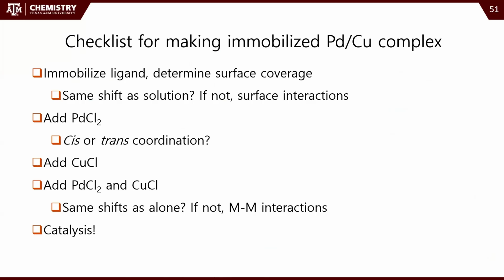This is kind of a tall order, and because it's an immobilized complex and the surface coverage of the ligand is not so good, we only really have solid state NMR as our analytical technique. XPS is too insensitive. X-ray diffraction is insensitive and gives not particularly useful data. Same with FTIR. You can tell they're different materials, but it's difficult to get real chemical information from it. So we just stick with solid state NMR, and we'll move methodically to make sure that we have each step looking okay.